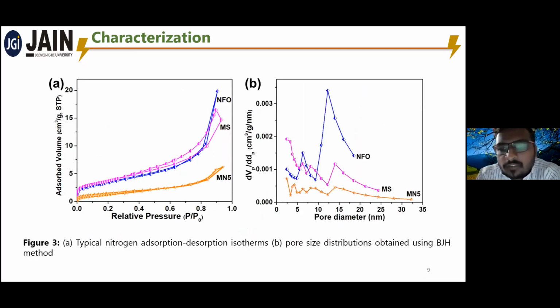To judge the surface area and porosity of the materials, we also perform the nitrogen adsorption-desorption method, and by the BJH method we calculated the pore sizes also. Compared to MoS2 and nickel ferrite, the surface area of our catalyst, MoS2 nickel ferrite with 5 mg addition, is less. This may be due to the nickel ferrite being anchored on the MoS2 structures, due to which the surface area is reduced. Also, it shows type 4 isotherms, and the material has a mesoporous structure, which is further beneficial for the electrochemical studies.